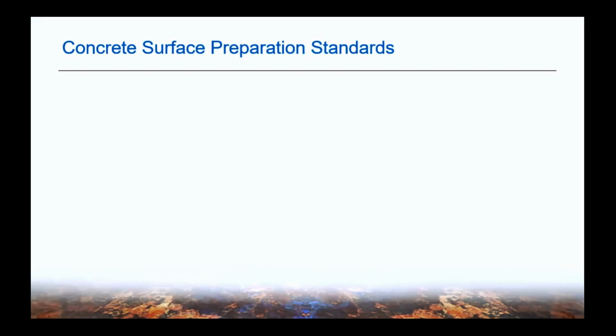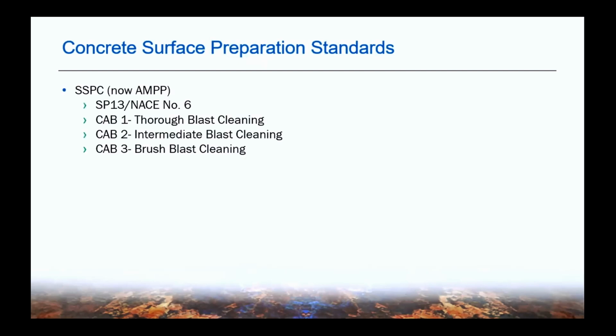So before coating concrete, it's important first to properly clean and prepare the surface. A great reference standard for that, many of you have probably reviewed and know the ins and outs of, but SSPC SP13 NACE is probably the most commonly specified concrete standard that I see out there. There's currently some debate whether it's a standard or a guide, but I'll leave that for another day and another discussion. But this is a good guide because it does give some inspection procedures prior to surface preparation, and then it also lays out some of the different methods of surface cleaning, and then it talks about some of the different methods of surface preparation.